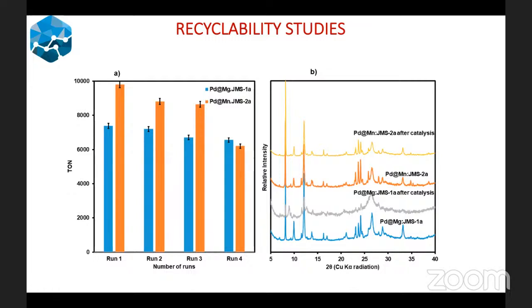In terms of the manganese or magnesium being active, we could not get a proper model to use. What we did was to take the metal salts that we used during synthesis of the MOFs to see if they have an effect towards the formation of formate. Under the conditions that we used, we did not observe any formate being produced. Of course, like you rightfully pointed out, we know there are some reactions catalyzed by manganese in the literature with very good yields. But in our case, when we used the metal salts applied in the synthesis of the MOFs under homogeneous conditions, we did not observe any formate being formed.